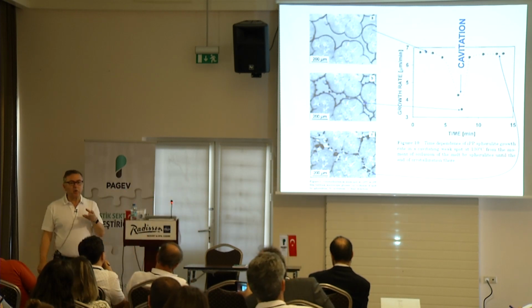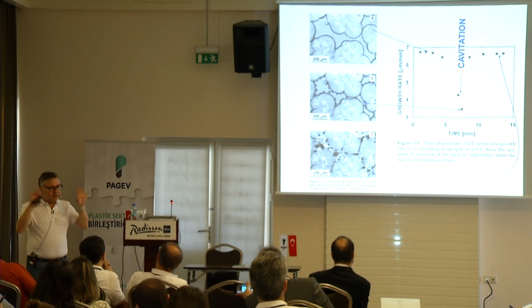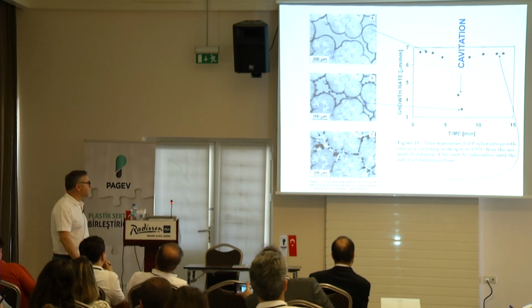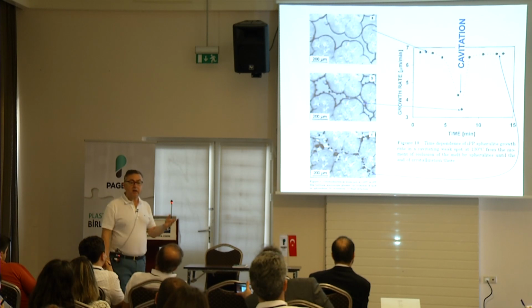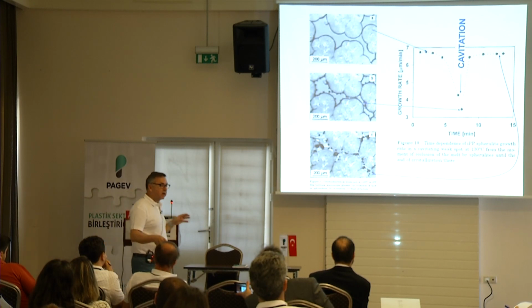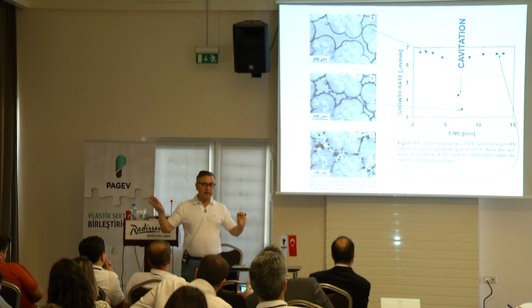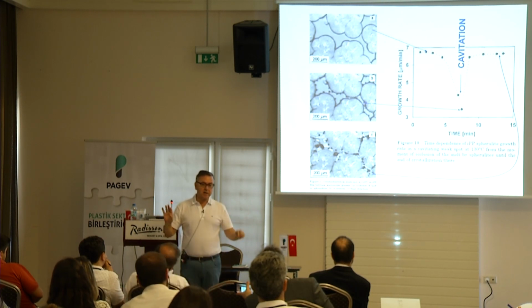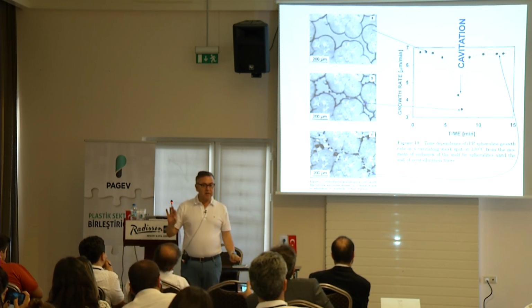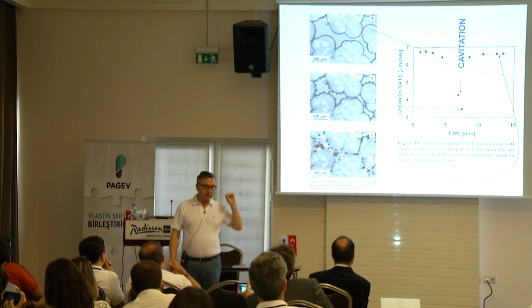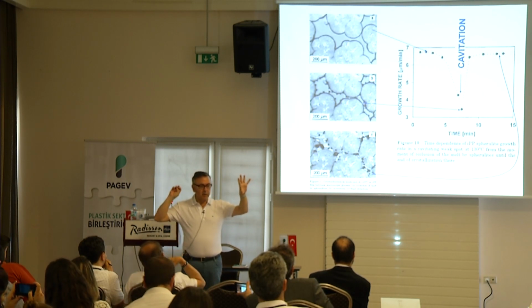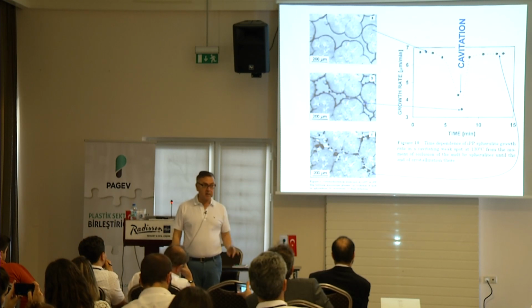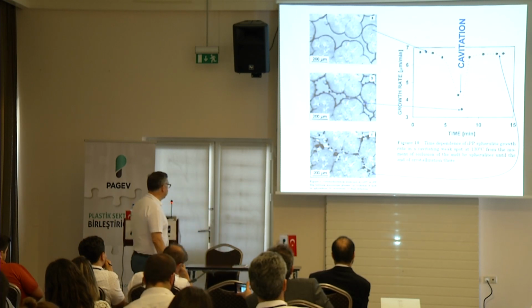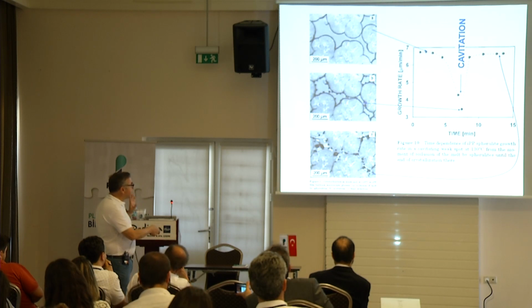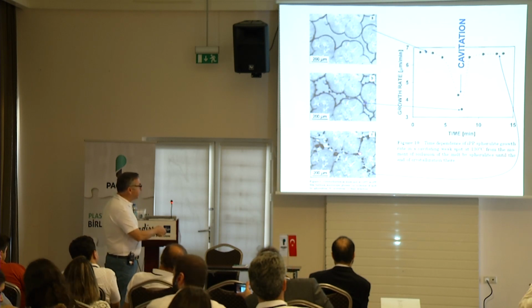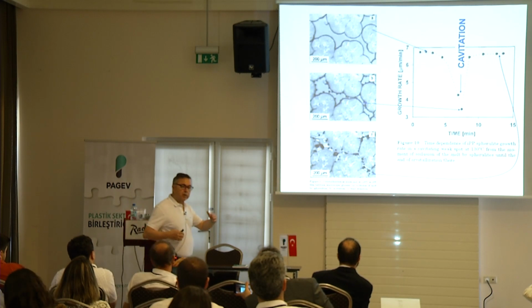So it always helps to have a homogeneous evolution of structure. That's why, for polymers, classically speaking, there is a correlation between brittleness and spherulite size. The smaller the spherulite size, the tougher the material gets. The larger the spherulite size, the more brittle the semi-crystalline material gets, always. It's all because, at the minimum, even if you don't have bubbles between the spherulites, the growth phenomenon